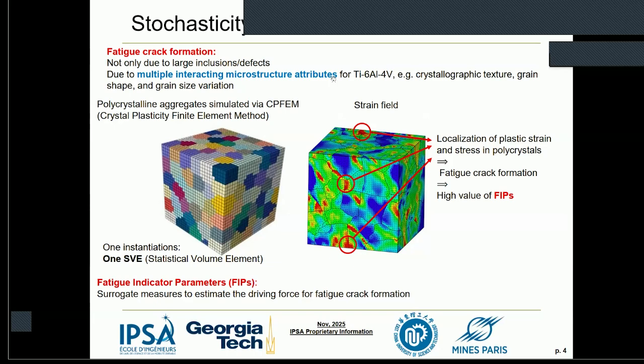If we build up a crystal plasticity model with one SVE, a statistical volume element, including around 200 grains, after the cyclic loading, you can see this is, for example, the strain field. There are some hot spots in the particles. This is the localization of the plastic strain and stress in the particles, and we can expect that there will be some fatigue crack initiation in the particles.